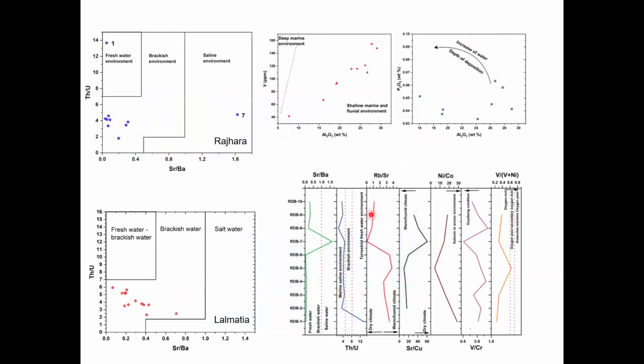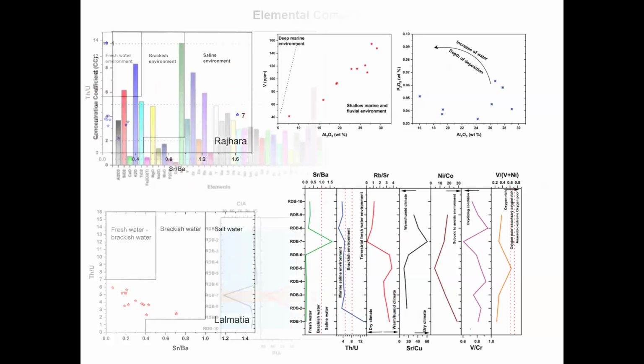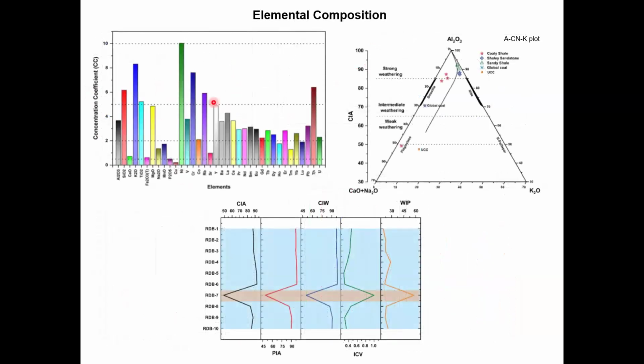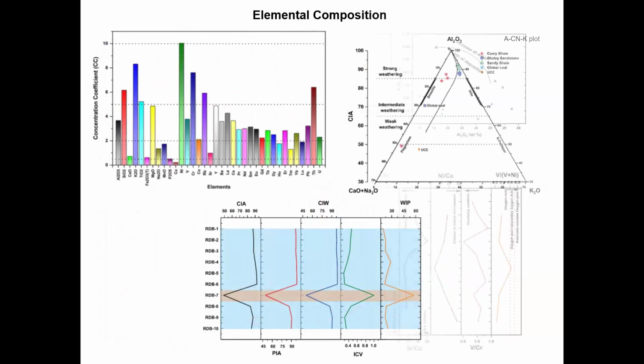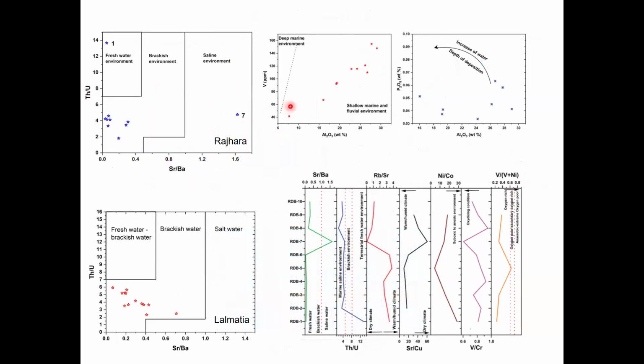Some other plots were also made based on elemental ratios like thorium and uranium, strontium and barium, etc., suggesting that most of the samples were formed in a brackish water environment. One particular sample, number 7, was formed in a saline environment, which we are getting over here also. The RDB7 sample is showing a different environment, most probably because it was formed in a marine influenced environment, which is again supported by